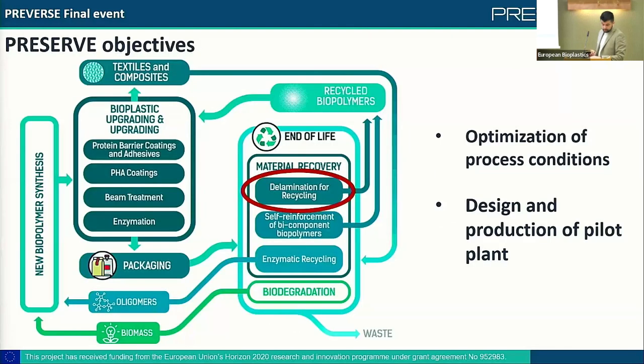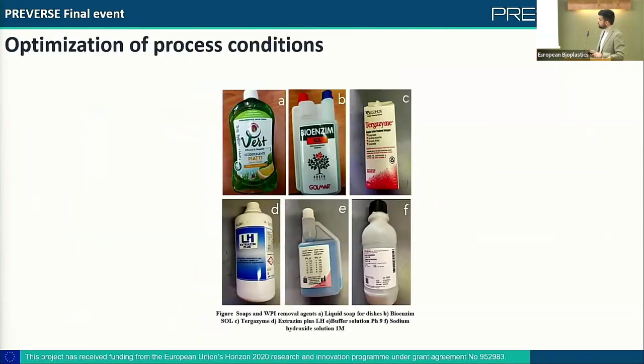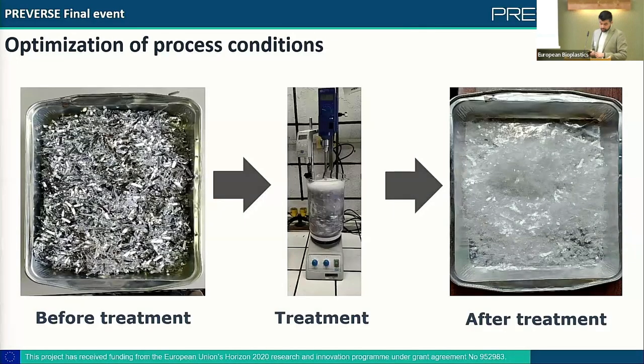In the first part of the work, a screening of different commercial soaps and substances, such as saline, enzymatic soap, and alkali solution, was carried out to assess which are the most effective in removing the whey protein, in order to select the best combination of solvent and process condition. After this, the process was scaled up in order to identify and develop the optimal process condition. In this phase, the optimal solution ratio was assessed, and how often the solution could be used in such a way as to minimize the use of water and soap.